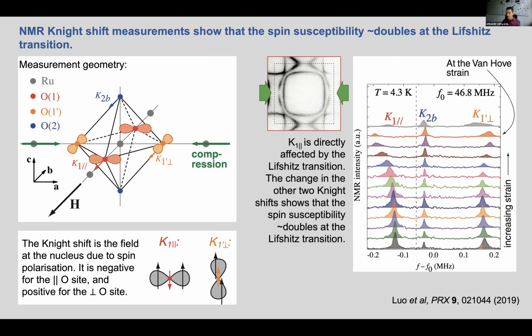And as they strain the sample, what they see is that the Knight shift of this peak increases and reaches a maximum at this strain here, right at the Lifshitz transition. It's a little bit harder to see for the apical oxygen sites, but as a fraction of the frequency shift, they see the same enhancement. And from this, they extract that the spin susceptibility at the Lifshitz transition is about double what it is in unstressed strontium ruthenate.